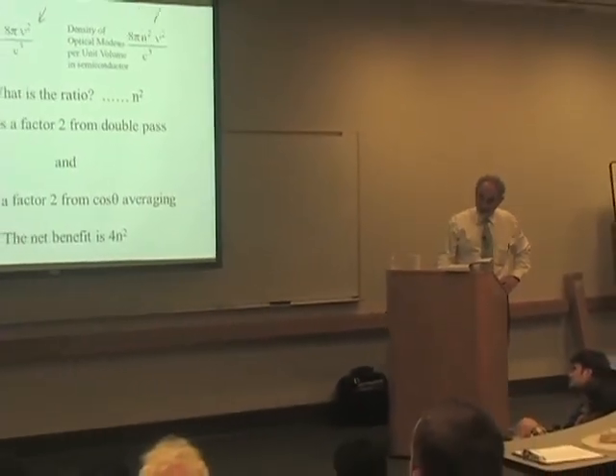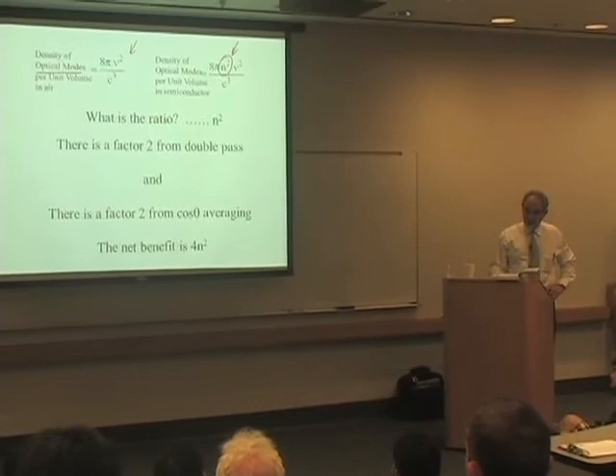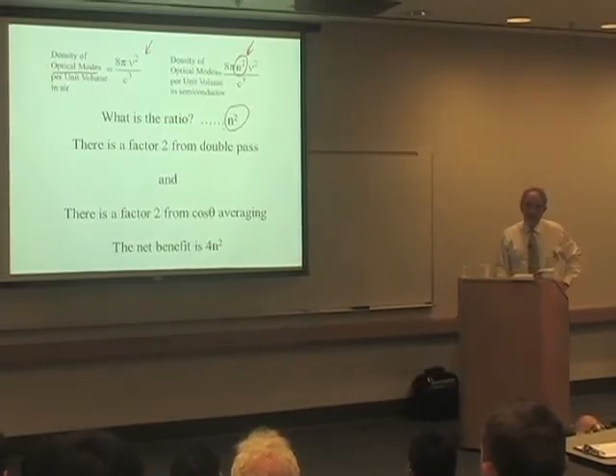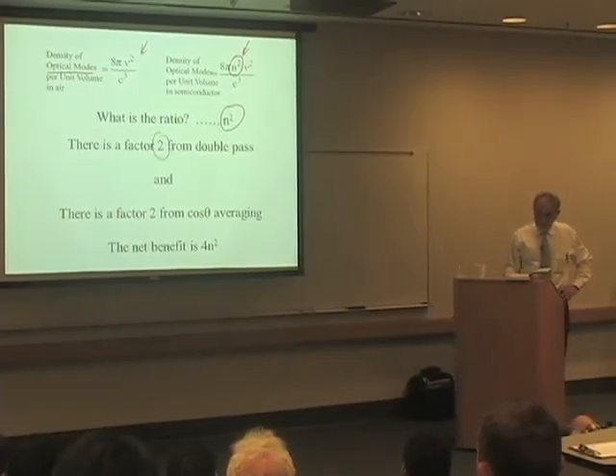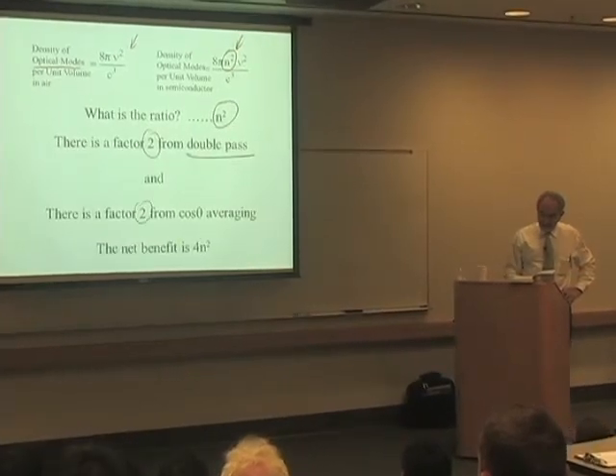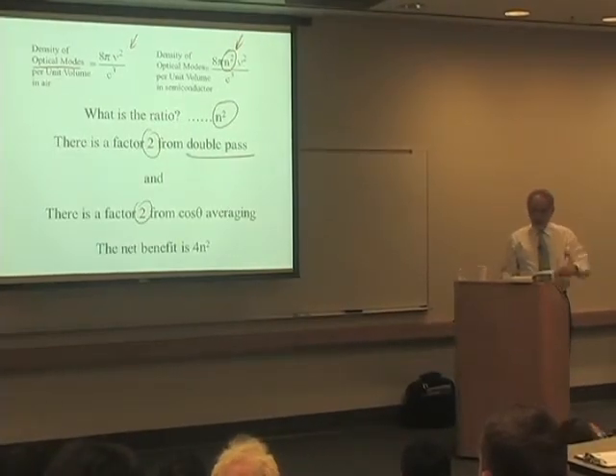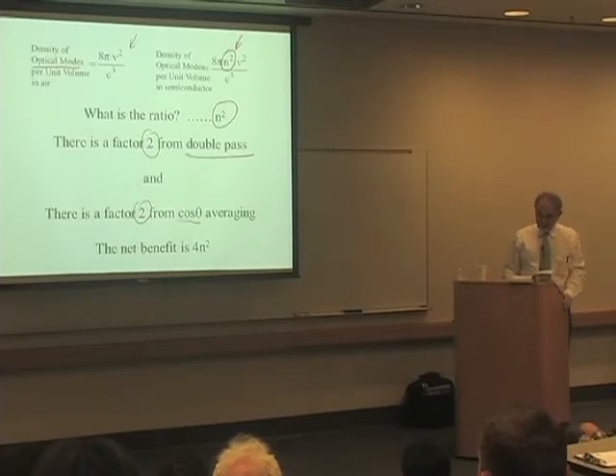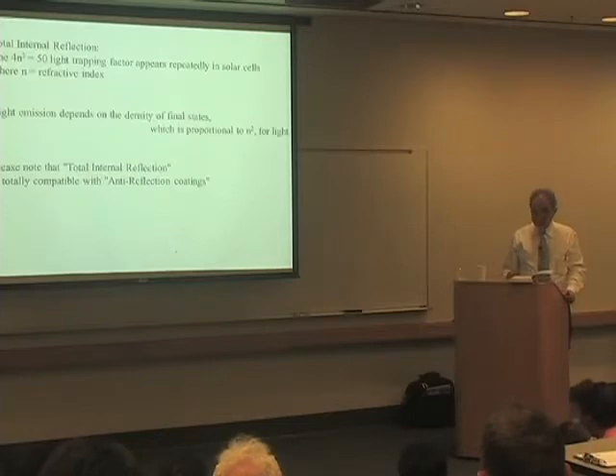Look at statistical mechanics, it's really all about statistical mechanics. You look at the density of optical modes. This is the formula for the density of optical modes. If you're in a material with a high refractive index, you have n squared. So that's where you get your first n squared. Then you get another factor of 2 from double pass. And you get another factor of 2, because if you're at an oblique angle, you have to average 1 over cosine theta, and that averages out to 2. So the net benefit, 2 times 2 times n squared, is 4n squared. So it's a very substantial benefit.